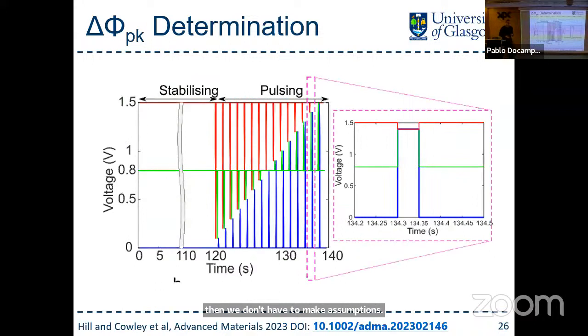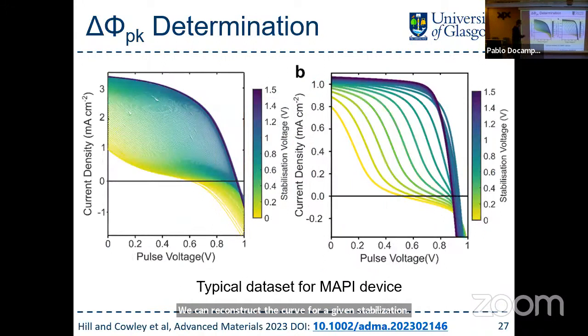Okay, so how do we measure it? We stabilize the cell at a particular voltage, and then we quickly pulse to a probe voltage, measure the current at the probe voltage, and then we can do this for a series of probe voltages. We can reconstruct the JV curve for a given stabilization bias. This is what it looks like. The yellow one is when you stabilize the cell at 0 volts and you probe. And then the really dark one is when you're getting closer to the open circuit voltage of the device. This is the experimental data, and this is the simulation of the same data set.